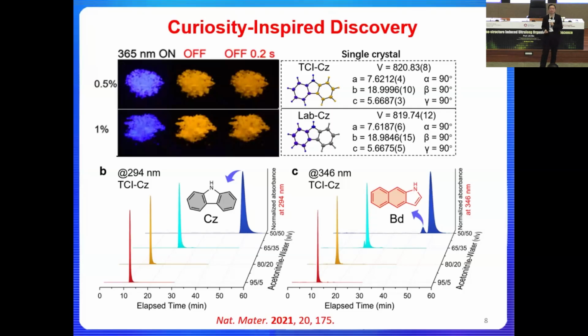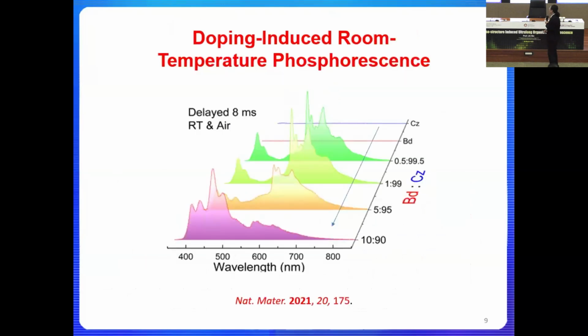So that's one piece of evidence indicating it is not the original chemical, but rather this 0.1% to 0.5% of the isomer that coexists with the original compound that gives you all the observed phenomena. All right, so the extreme case can be demonstrated here. If you look at the carbazole itself or the BD in the solid state, they didn't show any obvious fluorescence or phosphorescent signal. Now, if you mix a very small amount of the BD into the CZ, it's kind of like an alloy, but a small amount of dopants of BD incorporated into the CZ to grow a crystal. And amazingly, you will see that a new peak emerges with the increased concentration of the dopants. And then it will decrease because of the triplet state aggregation at a much higher concentration that will quench the phosphorescence.